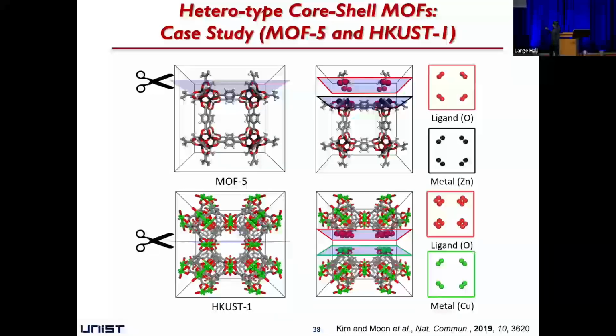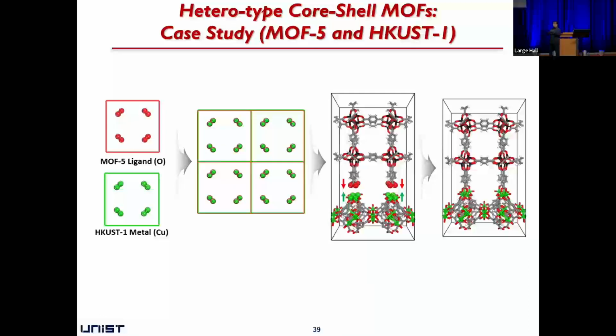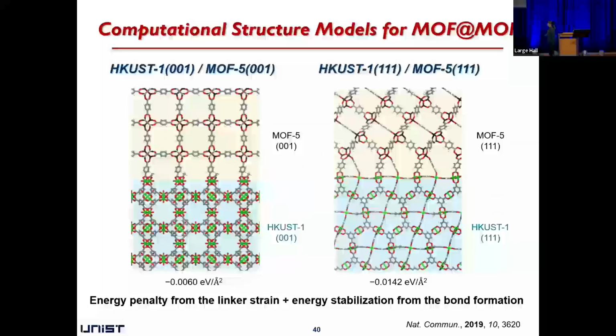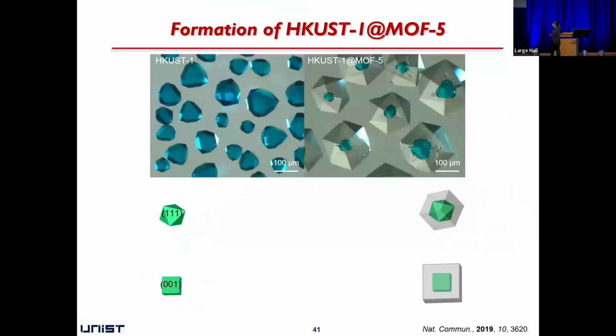So this is the chemical connection point of MOF5. This is the chemical connection point from HKUST-1. Then next, we superimpose these two positions, right? The ligand from MOF5, and the metal from HKUST-1. Then now we can tell that, oh, it can make a very beautiful interface, okay? It can make a coordination bond because it has good lattice matching and the location of a chemical connection point. After considering the energy penalty as well, then we try to start the synthesis. It can increase the possibility of a synthesis.